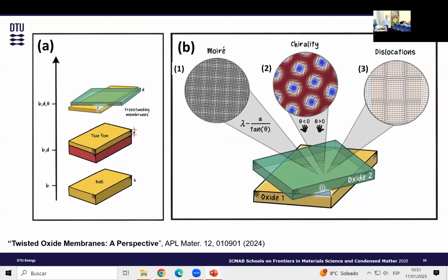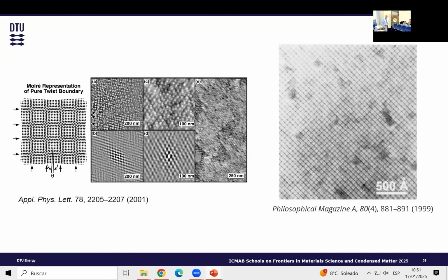The reason why we also thought about dislocations is the following. This is an example from a long time ago. Some people worked on silicon. They took two thin silicon wafers, put them together and twisted them. So this is the twist, this is the Moiré, and this is the dislocation net. This is from another paper. So you get a dislocation net at the interface.